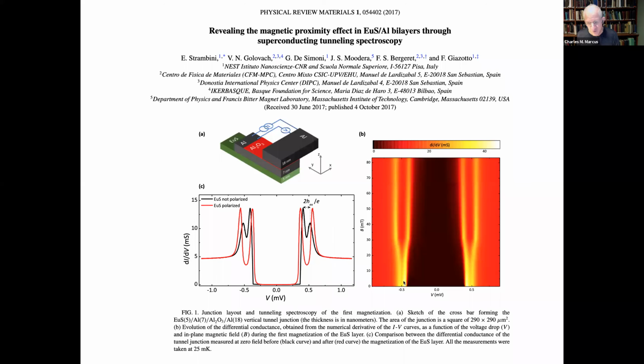One is that the field at which that saturates when you apply a magnetic field is quite small. Here, 30 millitesla of applied magnetic field produces the Tesla scale exchange field inside of this aluminum. And again, I want to just emphasize the same point I already made. The europium sulfide insulator, it's a ferromagnetic insulator, inducing a Tesla scale splitting of the superconducting BCS density of states inside of the thin aluminum in an external field, which is presumably magnetizing and removing the domain structure of the europium sulfide. It's a ferromagnet. In about 30 millitesla, producing this large exchange. That's the one important feature that I want to point out.